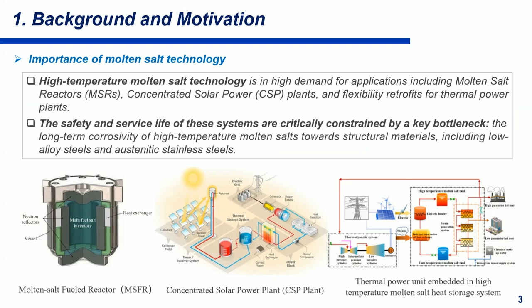The safety and the service life of these systems are critically constrained by a key bottleneck, namely the long-term corrosivity of high-temperature melted salts towards structural material, including low alloy steels and austenitic stainless steel.